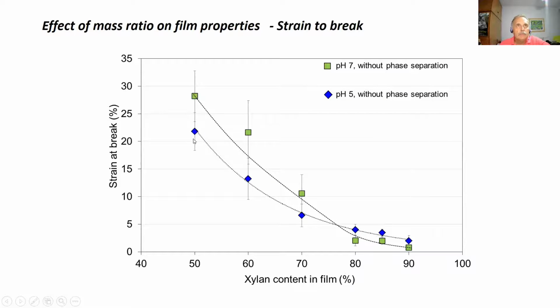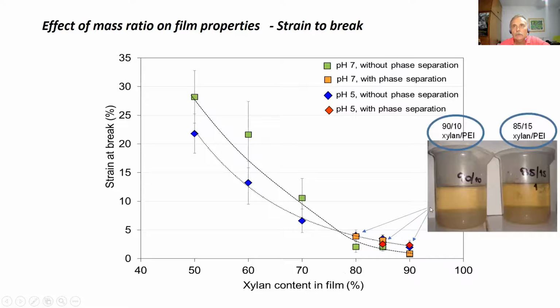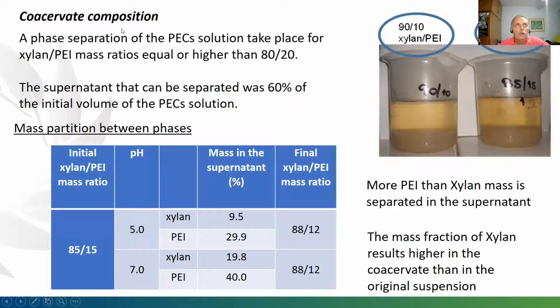The strain at break has the opposite situation. It's reduced when we increase the amount of xylan. And for the high xylan content, we can consider the coacervate, and the coacervate shows similar stress at break. How is the composition of this coacervate? We can see that this supernatant, that is 60% of the original volume, contains more PEI than xylan. So as a consequence, the mass fraction of the xylan results higher in the coacervate than the original suspension.